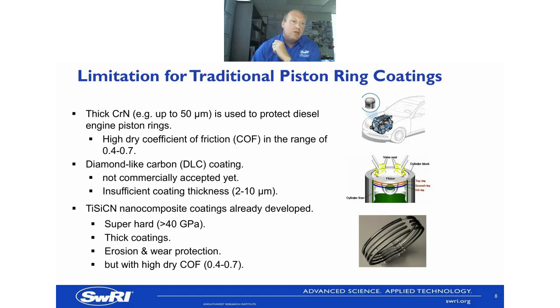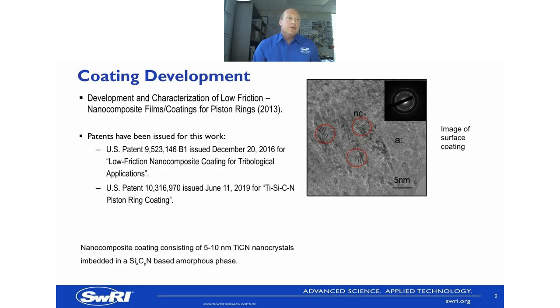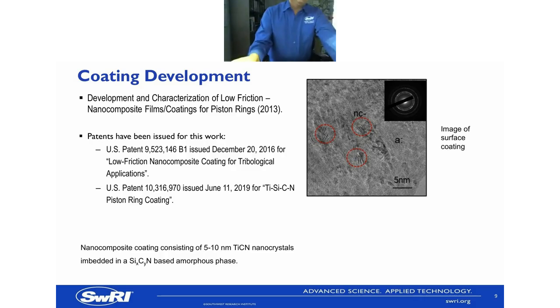And the TiSiCN nanocomposite coatings that we developed had some of the advantages that they were super hard, they were thick coatings, erosion and wear protective, but they did still have high coefficient of friction. Now, what we did is we developed the coatings further, and we did some more work on this, and we started to look at how we could do that. And what it is is a nanocomposite coating that consists of nanocrystals that are embedded in the silicon carbon nitride based amorphous phase. And we patented that, and we also patented the particular ring coating that we were looking at doing.